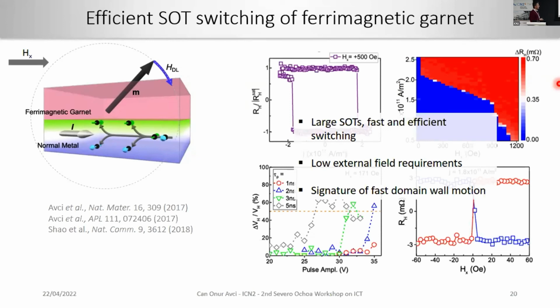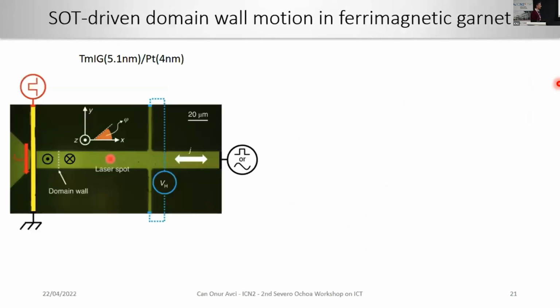So these early measurements that we have done show that very large spin-orbit torques can be induced on the magnetization in these insulators, and provide fast and efficient switching. And it has very low external field requirements. Actually here, that's down to 2 Oersted, which is very, very small, and also some signature of fast domain wall motion. Because we saw some signatures in the switching measurements, we wanted to study the domain wall motion.